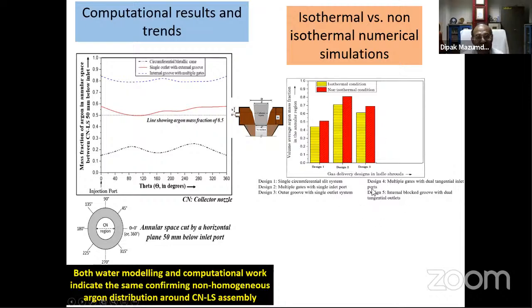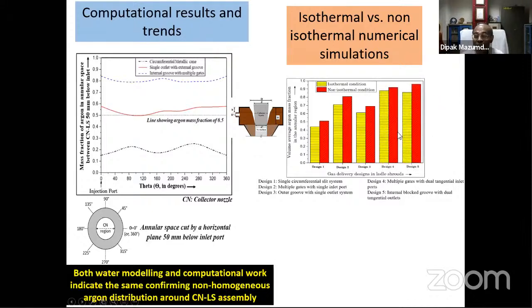Now, most interestingly, at this stage we understood that there exists considerable scope to improve the argon distribution around the shroud collector plate nozzle. So now if you try our design, which is a new design, that new design gives us a significant enhancement, almost 95% argon. While these lines correspond to one single line, this is the volumetric average of argon in this annular region. So the total residual oxygen here is barely 5%. It shows that design 4 and design 5, which had been evolved in our laboratory by carrying out a large number of computational trials, essentially tell us that the efficacy of argon distribution around the shroud collector nozzle can be considerably increased, and we can get almost the entire space filled with argon.